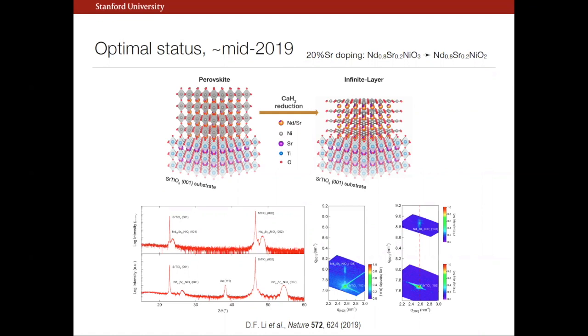So here's an artist's rendering of this deintercalation transition that leaves off the top structured capping layer. And by techniques like X-ray diffraction, it looks quite nice. This is the perovskite phase. We have the 001 or 002 diffraction peak. By deintercalation, they shift off to the right. And essentially all markers are pretty good. The thickness corresponds to the thickness limit of the film itself. You can see different fringes. And in all the cases I'll describe, our films are always epitaxially clamped to the in-plane lattice constant of the substrate.